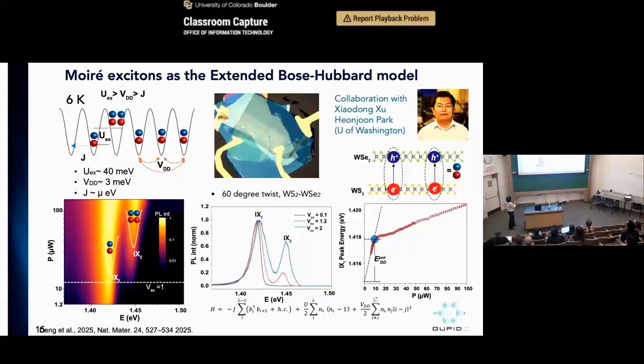The estimates here are coming from our diffusion measurement at a very low density, and that is probably the lower bound, but the upper bound, I would say, is still probably on the order of tens of micro electron volts, coming from theory calculation. So now we have this exciton in this extended Bose-Hubbard model, where you have a very strong on-site interaction and relatively strong dipolar interaction and much weaker tunneling. So we should be strictly in the Mott regime.